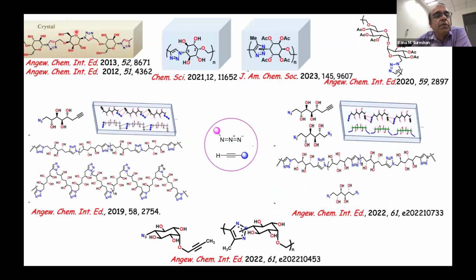This is again an unprotected derivative wherein you have a sugar, again galactose. We have got single crystal to single crystal transformation here. This is an interesting case. This is called inositol. This is similar to sugar, but it's not a sugar. This is a fully carbocycle, like a cyclohexane derivative having OH, and this is also C6H12O6. That means it's an isomer of sugar, and you can do polymerization of such sugars. Of course, this cannot polymerize by the natural way because there is no anomeric center here, unlike in sugars. So we can do this reaction.